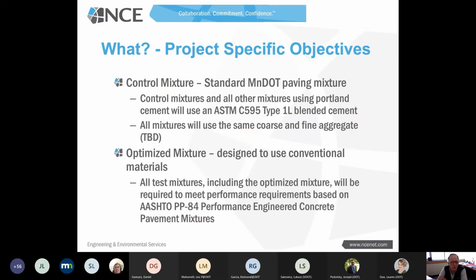And that is to look at optimizing the mixtures, which involves essentially removing the cement from the mixture and optimizing the aggregate gradation in order to achieve the same level of performance in terms of strength and permeability and other measures relative to the higher cement concrete mixtures.